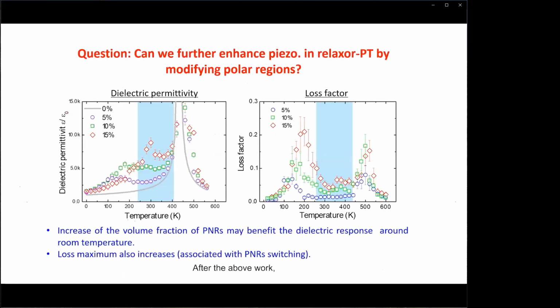After the above work, we asked a question to ourselves again. Can we further enhance piezoelectricity in Relaxor-PT crystals by modifying local polar nanoregions? Firstly, we did some simulation work. We found that by increasing the volume fraction of polar nanoregions, the dielectric response can be further enhanced at a specific temperature range. And the loss maximum may also become larger, as shown in this figure. These results tell us that if we can find some approaches to further enhance the volume fraction of polar nanoregions in Relaxor-PT, we can further enhance their dielectric and piezoelectric properties.